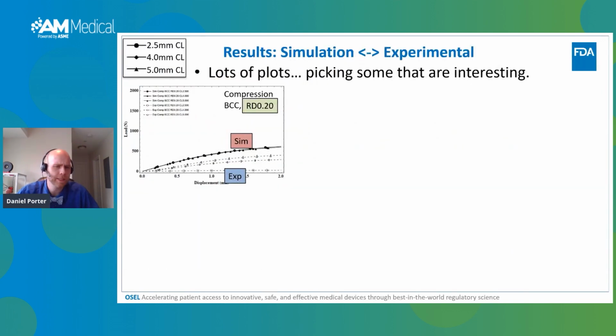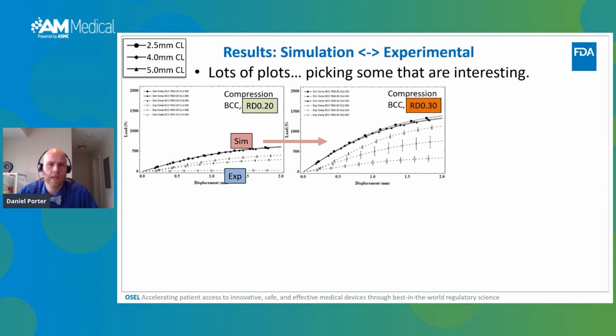All right. So this is simulation and experimental stacked on the same plot. Same legend, circles are smallest strut diameters. And what we're looking at here is going to be compression. Now note there's a lot of graphs due to the test matrix we have. So we're going to pick out some that we think are more interesting. We're going to start with compression, and we're going to put simulation, that's the dark lines, and then experimental is the dashed lines. And you'll see that the experimental actually does diverge quite a bit from the simulations.